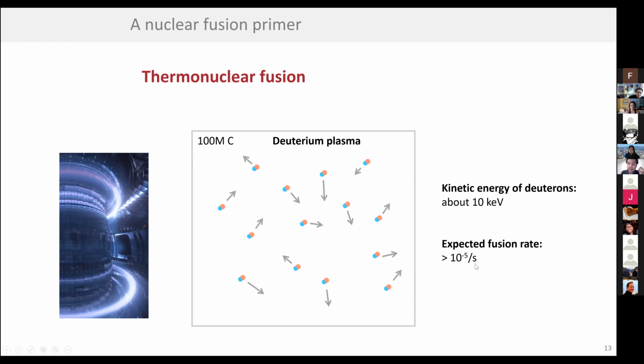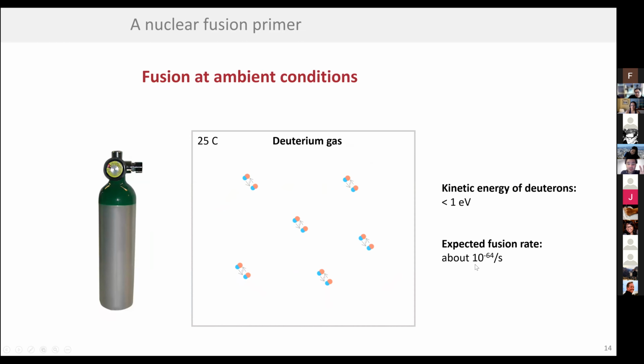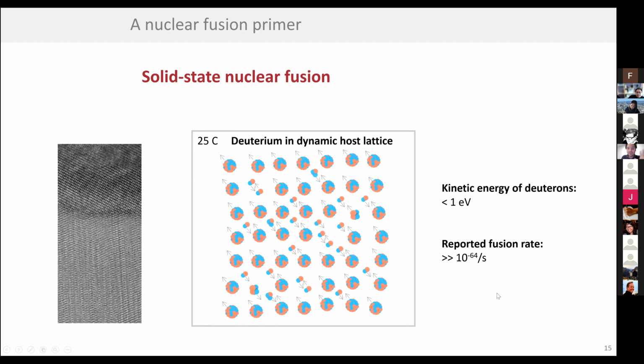And so here you would get a fusion rate, if you look at any two nuclei in your thermonuclear reactor, of 10 to the minus 5 per second or higher. And here the fusion rate has actually been calculated as 10 to the minus 64 per second per deuterium pair. So we can calculate a spontaneous fusion rate for a gas bottle at room temperature. It's just incredibly low, right? But that's in a sense the starting point for why people think this is not a worthwhile idea to look at in the first place. But how much would be different if you not just have a gas bottle, but you put the gas inside a metal? It's still room temperature, and it's still ambient pressure and whatnot. But well, we'll have to see about that.